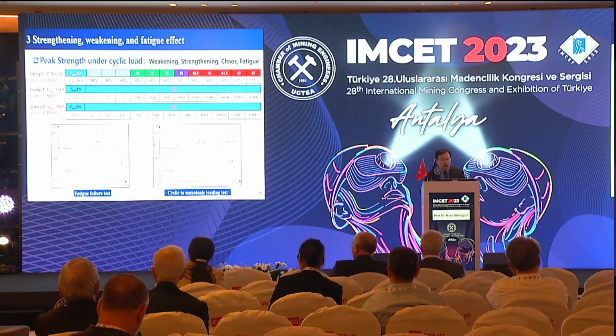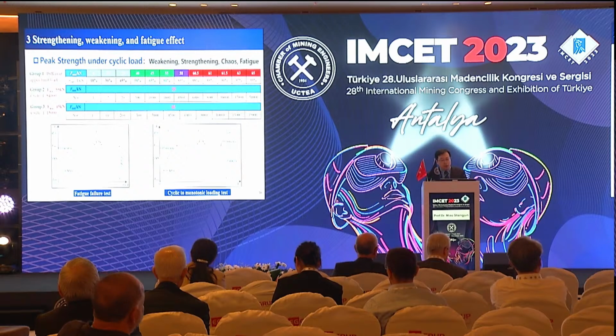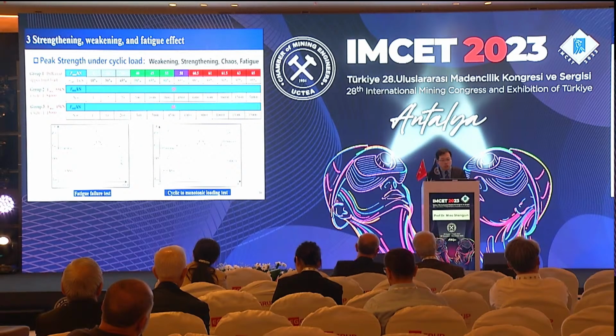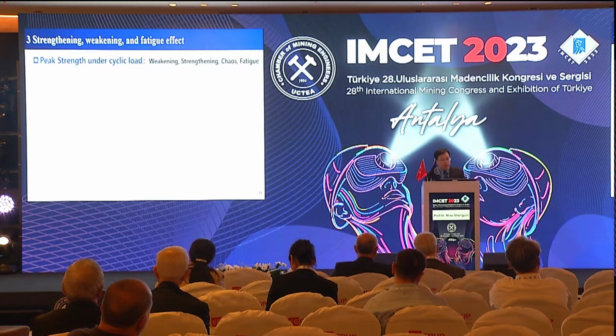If the specimen was not damaged after 3,000 cycles, then monotonic loading would be continuously applied until failure occurred, which was called a cyclic-to-monotonic loading test. Group 2 and Group 3 keep the upper limit load constant and change the cycle number, followed by monotonic loading. In Group 2 and Group 3, the upper limit loads are respectively 55 kilonewtons and 45 kilonewtons. Next, I will provide the detailed analysis of the results of this test.